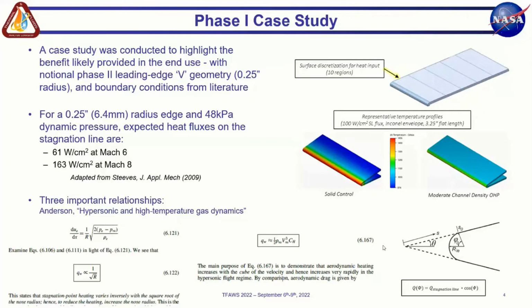There are a couple important relationships to understand the general thermal map. At the stagnation point, heat flux varies inversely with the root of the radius. So as you go to very sharp leading edges, the flux rises rapidly. As you go up in Mach number, the flux rises with the cube of the Mach number. Hence the general thermal problem as we push the envelope on these hypersonic vehicles. And lastly, how that flux varies radially as you move off the stagnation line: it drops off very closely to cosine as you move back around the leading edge.